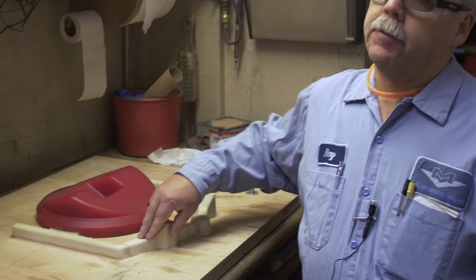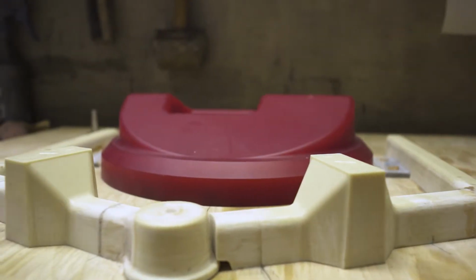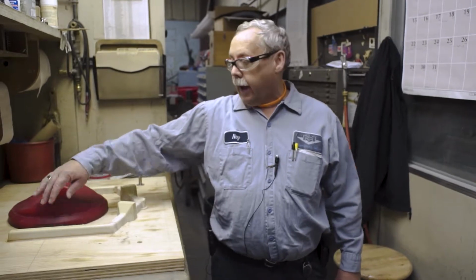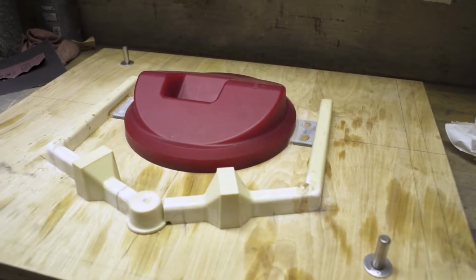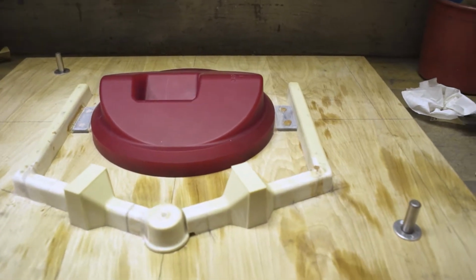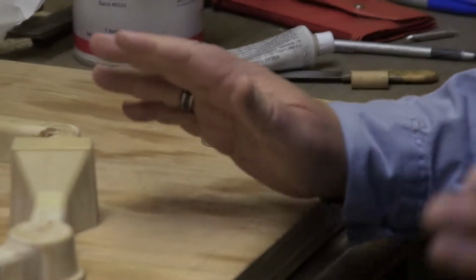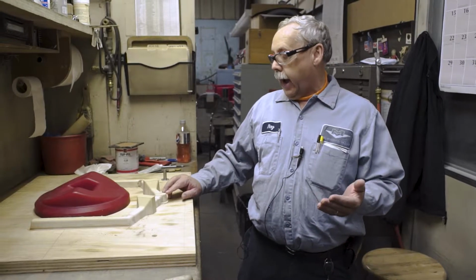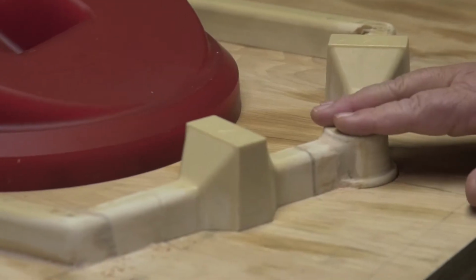And the next step in the pattern making process, they'll make a runner. This is the runner, the material to get the metal to the casting. We got a gate, which is the contact area between the runner and the casting. And this is the actual part, or what will be the casting. It gets mounted on a board, and then we mount pins on the board because we make the mold in two halves. This happens to be the drag half of that mold, or casting. The drag meaning the bottom.